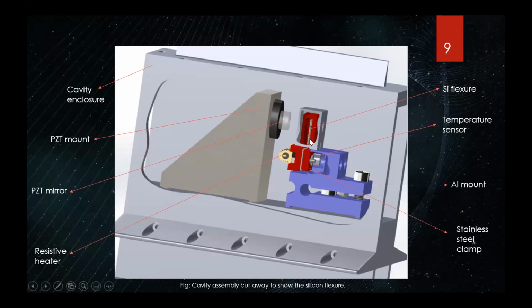We have the PZT mirror and our flexure. The base of the flexure is clamped between 2 stainless steel clamps that are on this aluminum mount. You have a resistive heater on the front side to heat the flexure and maintain its temperature at 123 Kelvin. And immediately on the back side, you have a small temperature sensor for readout. And this is a cutout view. You can see that there are fins on either side of this cavity to increase the surface area for radiative cooling.